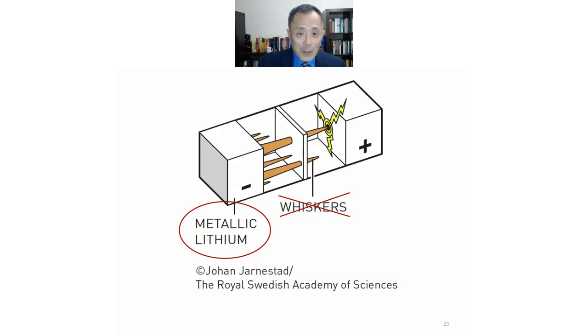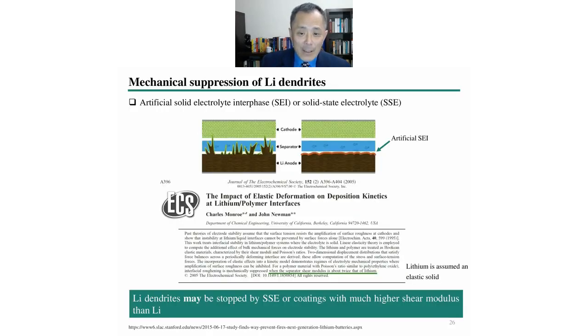There are two general approaches. One is to use what's called an artificial solid electrolyte interface. But in the surface engineering community, that will simply be a coating deposited on the surface of lithium metal next to the separator. And the goal is to suppress lithium dendrite growth.